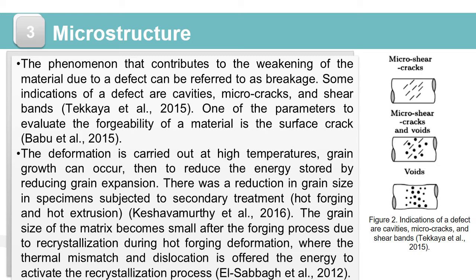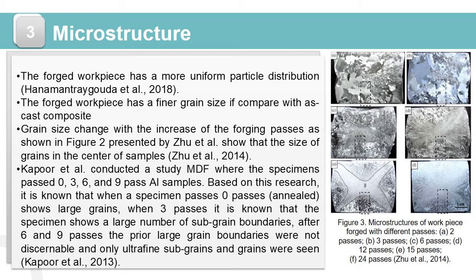The grain size of the matrix becomes small after the forging process due to recrystallization during hot forging deformation, where the thermal mismatch and dislocation provide the energy to activate the recrystallization process. From some papers, we know that the effect of forging on the microstructure is that the forged workpiece has a more uniform particle distribution compared to the workpiece that is only cast.